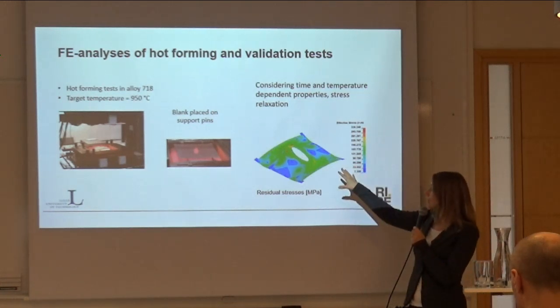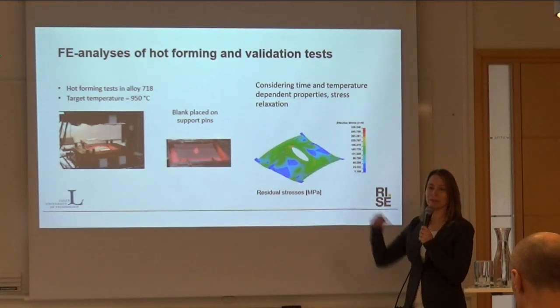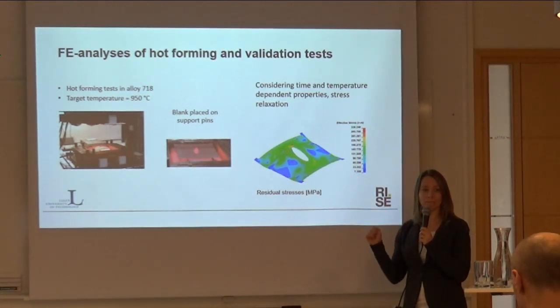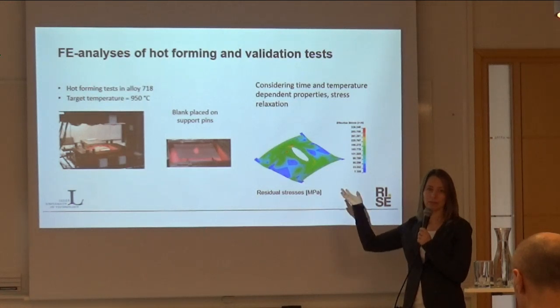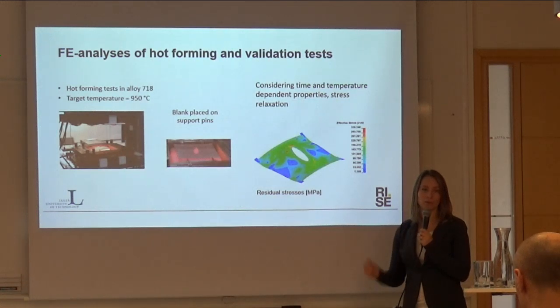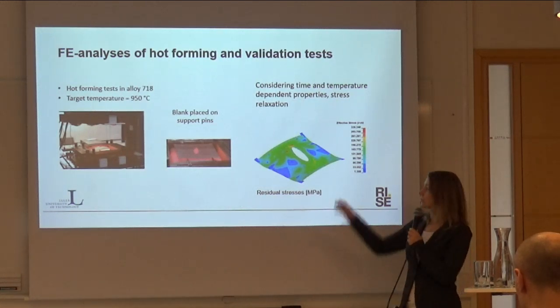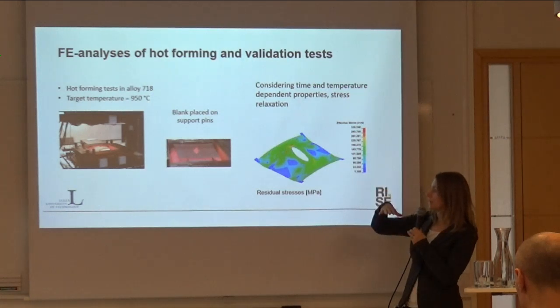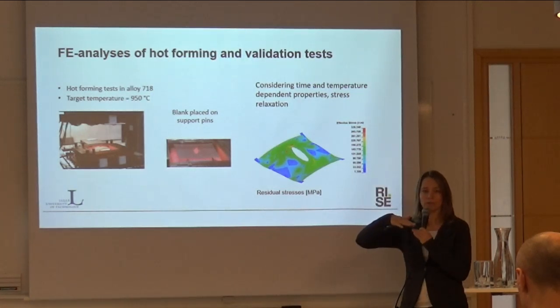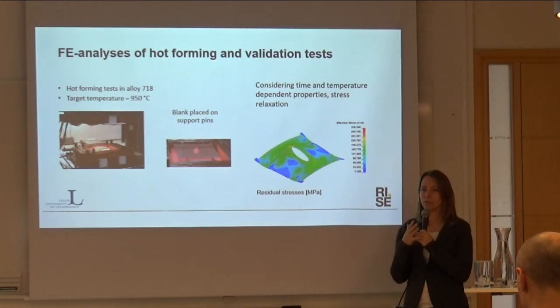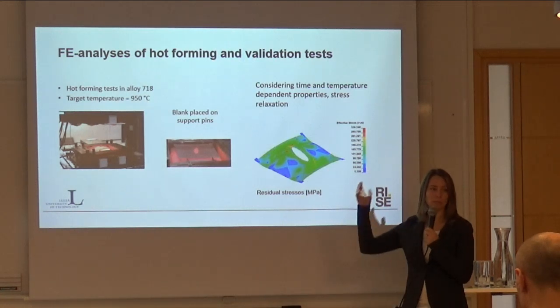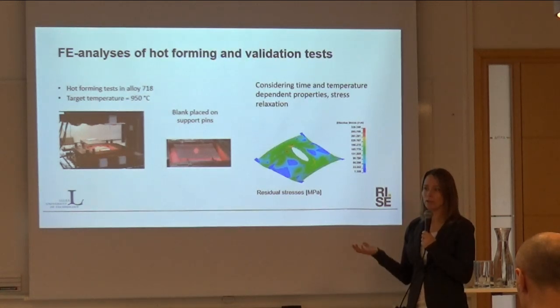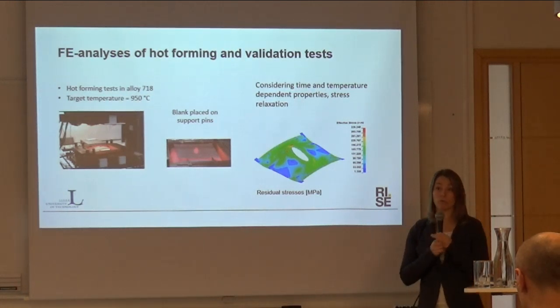And we can use the property of the material where the stresses relax with time. So we consider the time and temperature dependent properties in order to relax the stresses and thereby reduce the amount of spring back. Because if we had a forming procedure at room temperature, it's a very high strength material, so it will just spring back and we will end up with no geometry at all. But by using hot forming, we can produce parts much cheaper and faster than with a cold forming procedure.